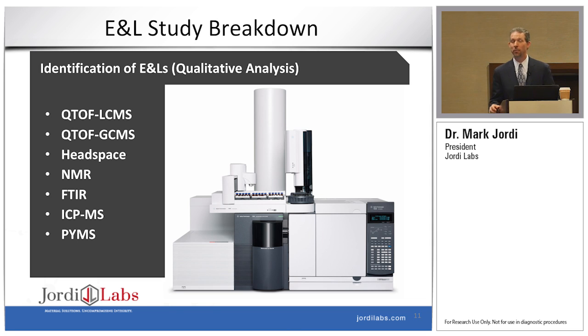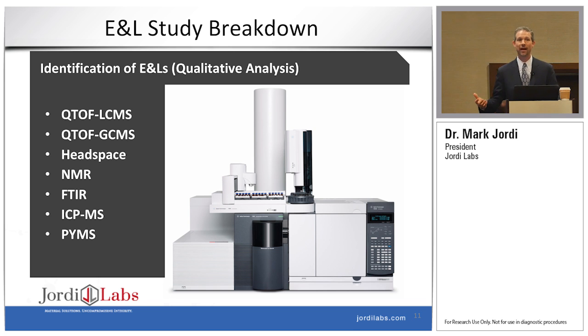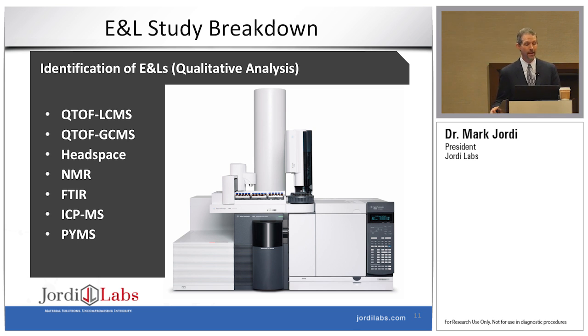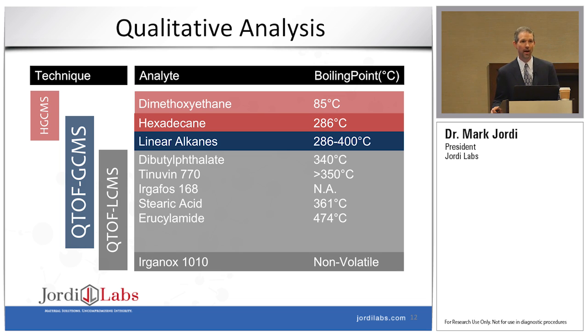After we have prepared those extracts, we're going to run methodologies like these. Typically in our laboratory, we'll use QTOF LCMS and QTOF GCMS because they're the best tools for identifying unknown materials. We'll then also do Headspace, NMR, FTIR, ICP-MS, and PYMS. We use a wide variety of tools because any one tool is going to have blind spots.